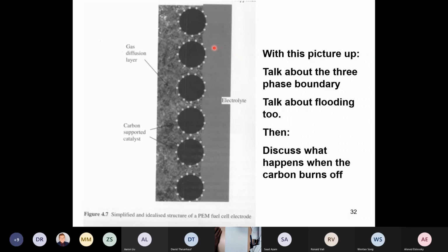Here comes the proton. The electron has to come through the carbon fiber paper, through the carbon black, to the surface of the catalyst. Okay, and you want the proton and the electron to combine with oxygen to make water. So that means the oxygen in the air has to move through this carbon fiber paper and also appear at the same place. So you have to have electron, proton, oxygen right at this catalyst surface all at once. And that's called the three-phase boundary. You have to have a contact to the proton, the electron, and the gas.